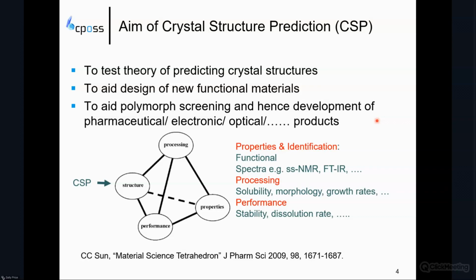And it's also increasingly used now just to aid the polymorph screening and the development of specialty organic products, particularly pharmaceuticals. And this comes from this very important link that the crystal structure prediction gives you the specific polymorphic structure, and it's that specific structure determines the properties, whether they're the functional properties or the spectra that you need for identifying the polymorph in any monitoring and looking for polymorphs, and also the properties that are important in processing it, such as the solubility, morphology, growth rates, and all of these interact to give you your performance of your product, including its stability, and for drugs, the dissolution rate is a key aspect.